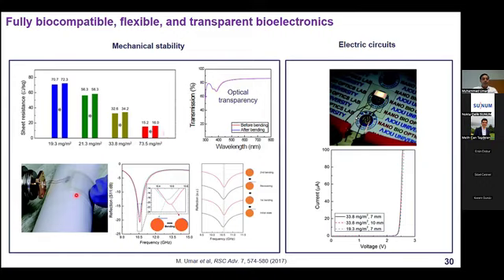And also we showed that if we have an antenna, when it is not bent, you can see the resonance spectrum of the antenna. When it is bent, the resonance spectrum is shifted to the higher wavelength. So this is the multiple bending of the antenna. This means the recovery of the sample is very good. So even after multiple bending, it does not affect the silk and silver nanowire-based electrodes and antennas.